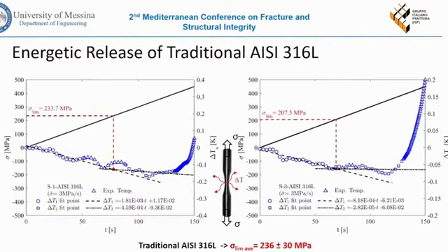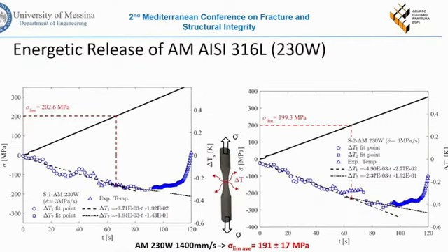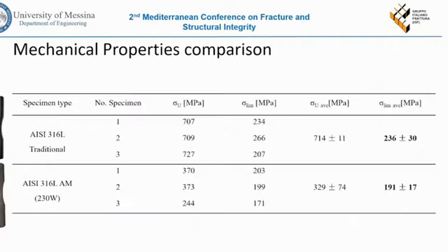Here we report also the other static tensile tests performed on the same steel. And here I report the tensile test performed on the additive manufactured steel. So we can see how the limit stress is considerably low compared to the traditional material. In this table, I report the ultimate tensile strength and the average limit stress of the materials.